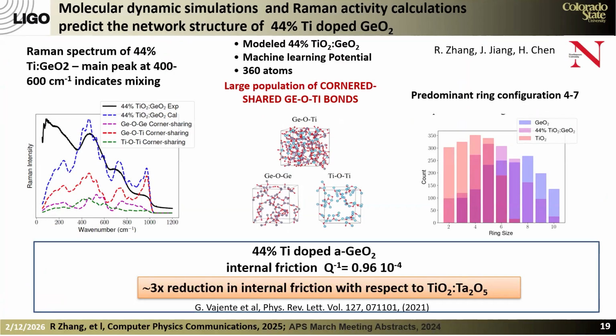Nevertheless, we have done also studies in the material. We looked at the Raman spectrum. In collaboration with our colleagues at Northeastern, we showed that indeed this particular composition is very special because we can form a network like I'm showing here, in which you see the majority are Germania or titania bonds, and these are forming a network in which all of these molecules are connected by sharing corners. And this is what we need to have low internal friction.